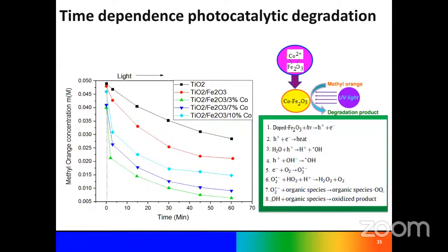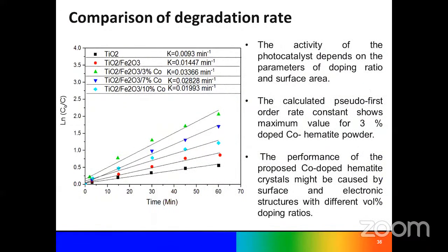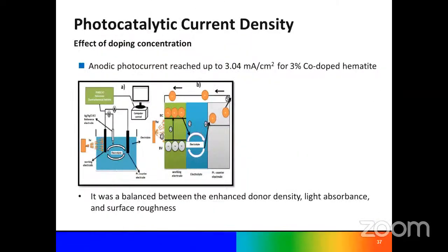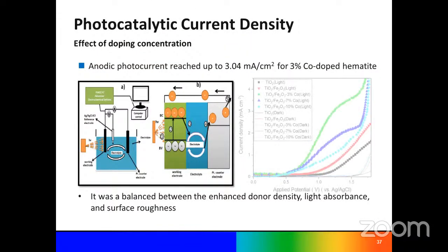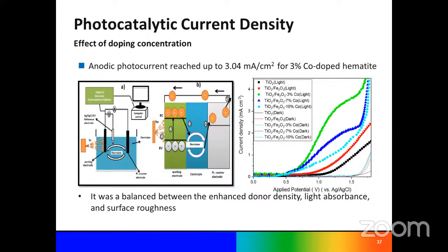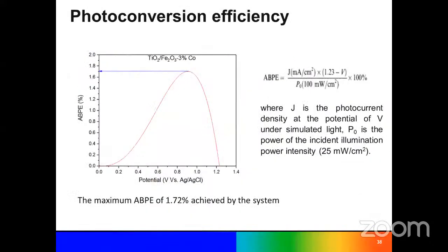And here we also studied the degradation mechanisms of these 3% cobalt doped hematite materials. And then we checked the kinetic behavior, where the kinetic rate is maximum in the case of 3% cobalt doped. Then we fabricated the photoelectrode and checked the photoelectrode properties. The anodic photocurrent reaches around 3.04 milliampere per centimeter square in the case of 3% cobalt doped. It requires a balance between the donor density, light absorption property, and surface roughness, all of which need to be optimized in this case. So here, the efficiency value reaches around 1.72%,